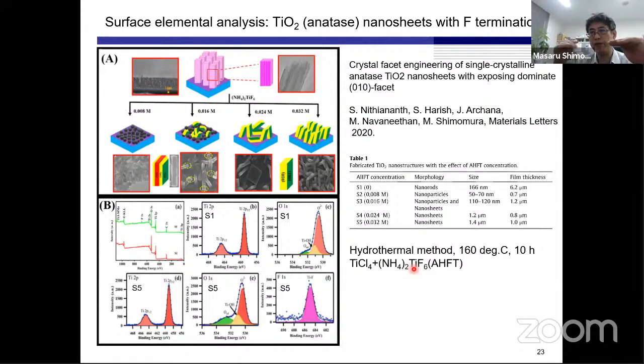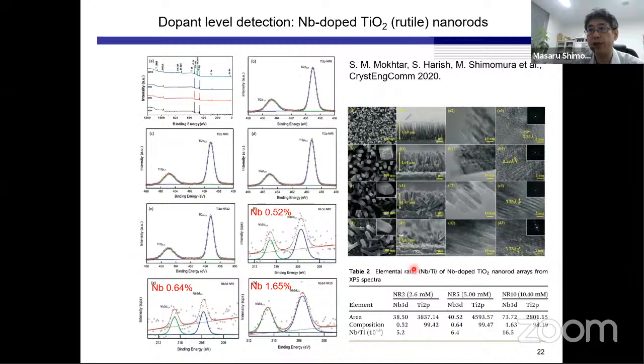But if you measure for a very, very long time in a limited energy region, then maybe you can observe it. For example, for this niobium peak, the student measured maybe over 1 hour, maybe 2 hours or something. If the accumulated data is summed, then it starts to show a peak. So please try a longer measurement period. That is the advice. If you still cannot observe it even after a very long measurement, then it is because of high background with low peak intensity.